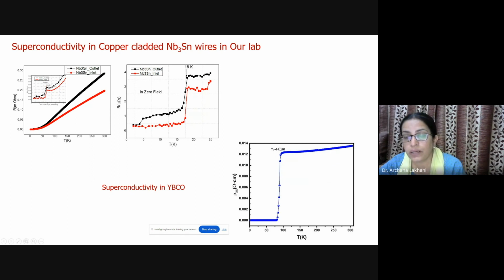In our laboratory, we have prepared a YBCO sample also. I'm just showing one typical curve for this. In it, the superconductivity occurs at around 92 Kelvin, and we see a sharp transition, with resistance falling exactly to zero at 92 Kelvin.